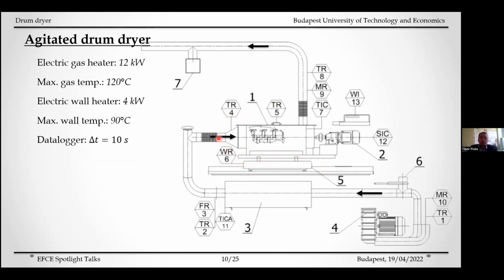The humidity of the drying gas entering and leaving the dryer is measured using a capacitive humidity sensor. Differential pressure on an orifice flow meter is measured by a transmitter to determine the mass flow rate of the drying gas. Thermocouples were used to measure the inlet and outlet air, wall temperature, orifice temperature, and atmospheric temperature. An infrared sensor in the middle of the dryer is used to measure the surface temperature of the particles.